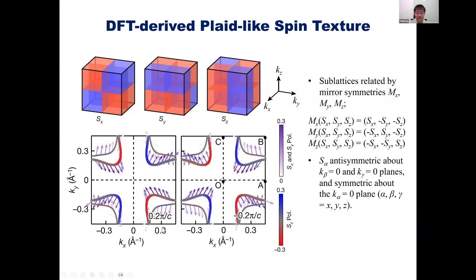This one is kz equals plus 0.2 pi, and this one is kz equals minus 0.2 pi. So between plus kz and minus kz, the spin also changes sign. This is the characteristic of this type of spin splitting, which is different from Dresselhaus and Rashba spin splitting. It also happens in the bulk bands, not the surface bands, as Rashba splitting does.